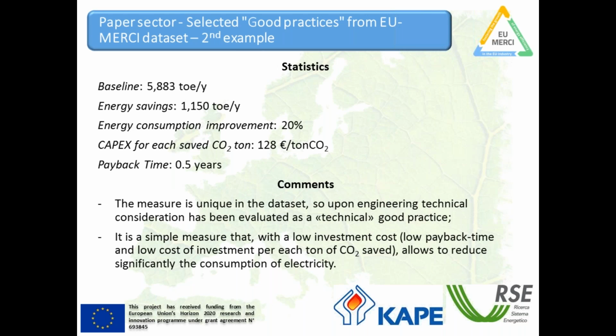Again, statistics. This was a single measure, unique in the dataset, so we only have one value for each indicator. Baseline is a little bit less than 6,000 tons of oil equivalent per year. Savings are around 1,000. The energy consumption improvement is around 20%. Here we have a good example of a measure that is not so expensive because we have very low capex for each saved CO2 and also very low payback time. Some comments: this measure is unique in the dataset.